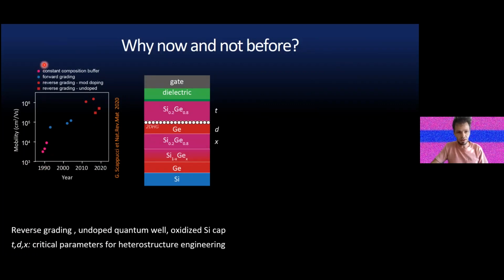people used to grow a constant composition buffer layer on top of silicon. So directly a silicon germanium high percentage. And that really had a lot of defects and dislocations. Then we moved to forward grading, meaning that you slowly introduce germanium up to 80%. But that yielded really thick layers. And again, with thick layers came a lot of dislocations and defects.